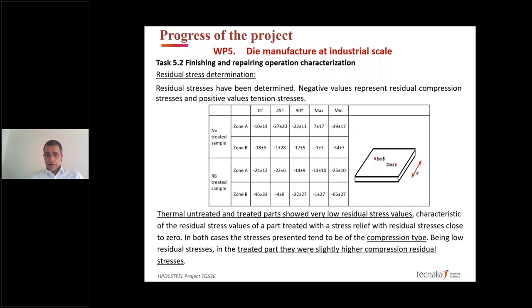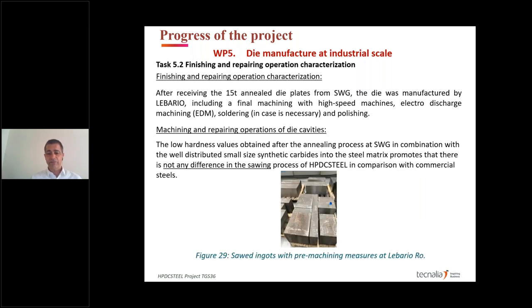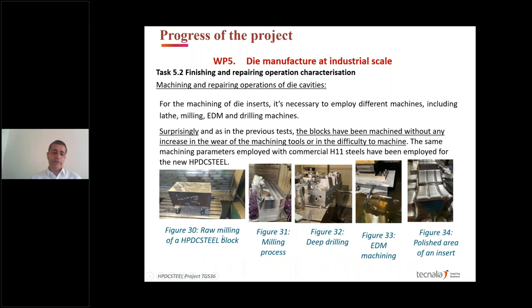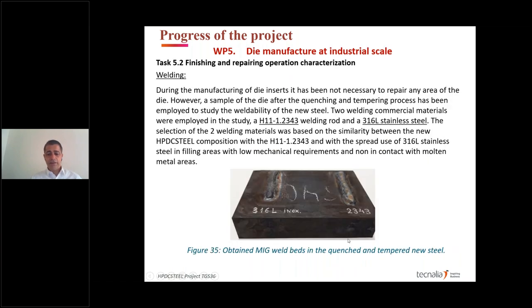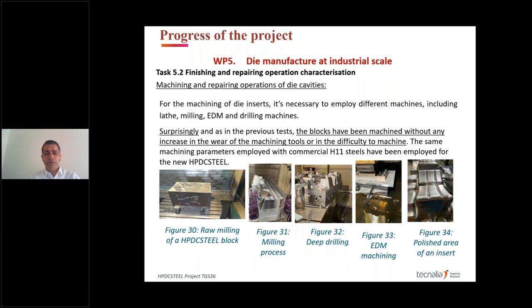We also made the residual stress determination, with the same results that we had before. And finally, we sent the die plates from SWG to Levario. We started the machining of the die, with all the operations: roll milling, milling, deep drilling, and so on. The most important thing is that there was no difference between the standard machining of premium steels and this one. The only difference was 1.5% more tool wear, which we think is also a very small percentage.